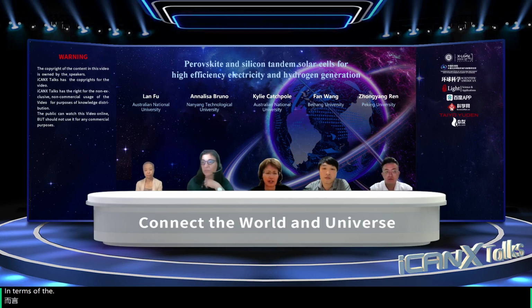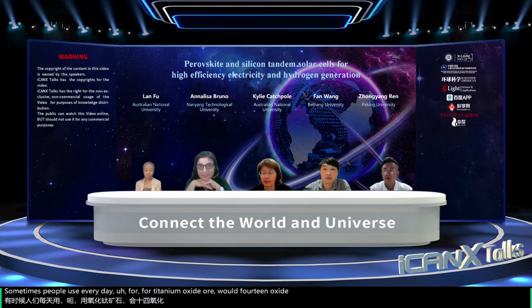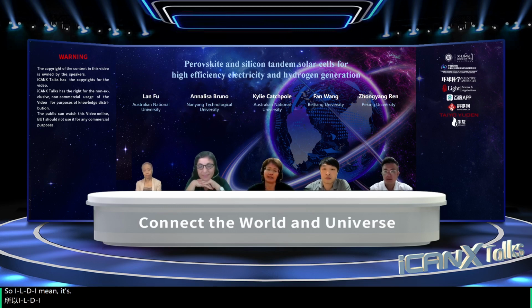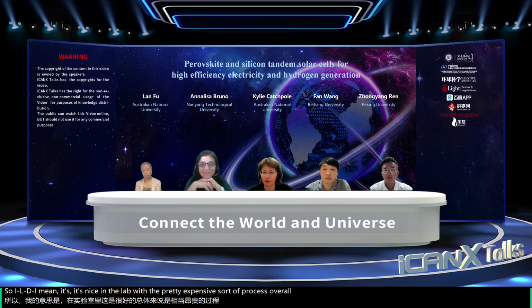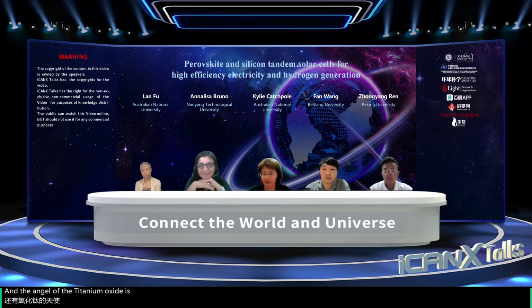In terms of the different ways that you can produce the layers, sometimes people use ALD for titanium oxide or tin oxide. ALD, I mean, it's nice in the lab, but it's a pretty expensive process overall. Certainly, the ALD titanium oxide is not really conductive enough. Other techniques use tin oxide nanoparticles. I mean, sputtering is really nice as an industrial type process.